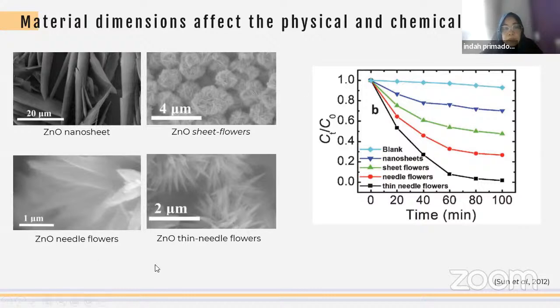You can see that this of course affects the optical properties like absorbance, reflectance and emission, and will affect the photocatalytic properties. When we use nanosheets, the blue line here, the reduction of the catalytic properties is quite slow. But when you apply the thin needle flowers or the sheet flowers, the green, red and black lines here, the catalytic performance gets better.